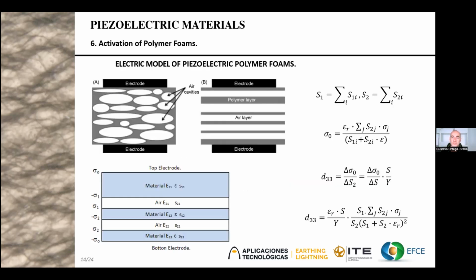To model these materials, we can see that the voided complex structure of the polymer can be simplified by air and polymer layers, with a layer on the top and bottom for the conductive electrodes. The structure comprises solid layers and an air layer, called S1 and S2 respectively, and the charges on the top and bottom of the air gap are taken to be equal in magnitude, since it is assumed that they originate from the discharge in the air gap during the poling, because we need to produce these charges only in the air gap.